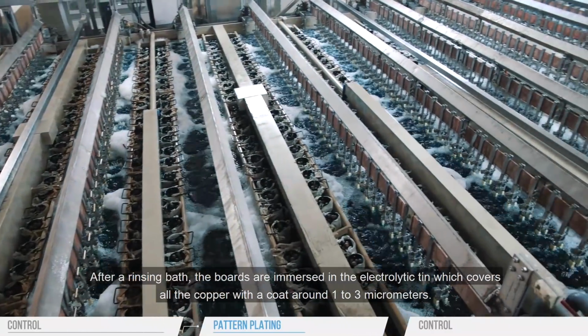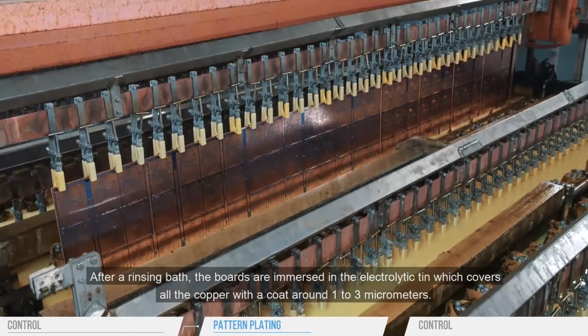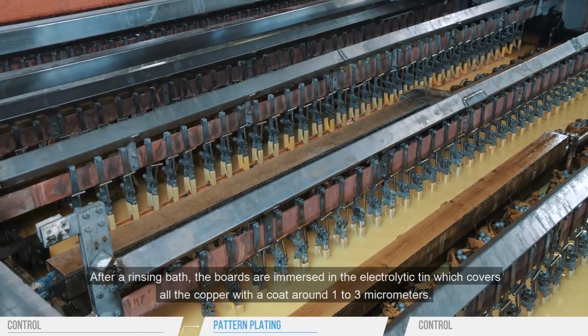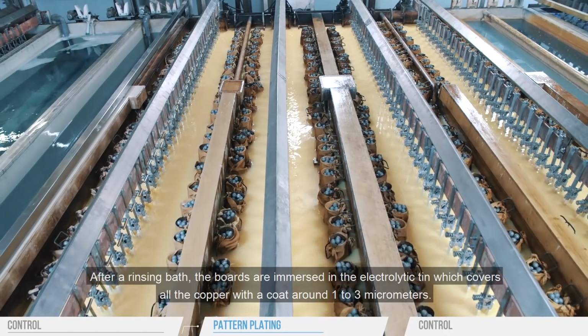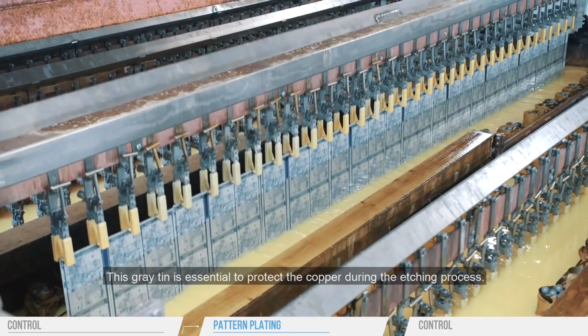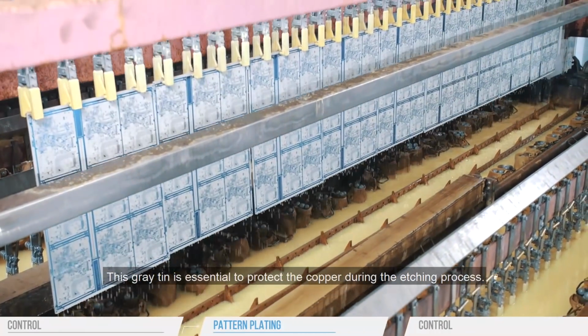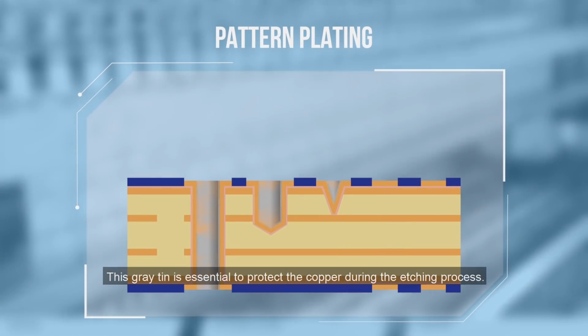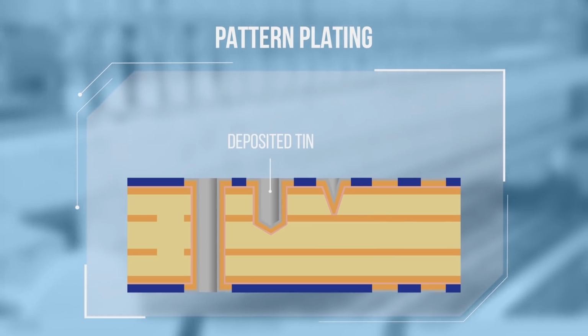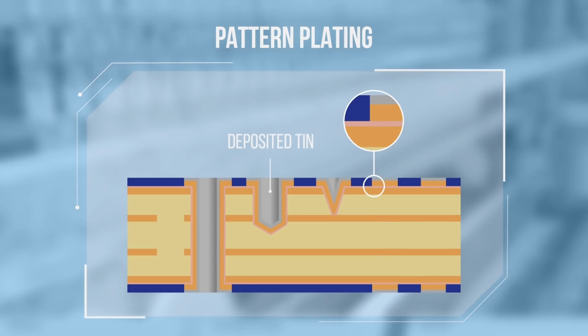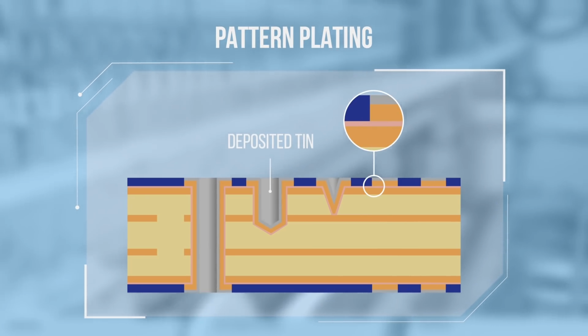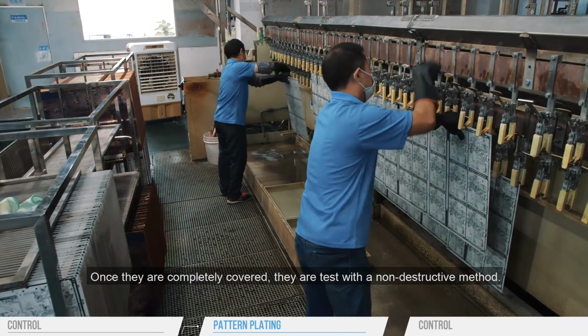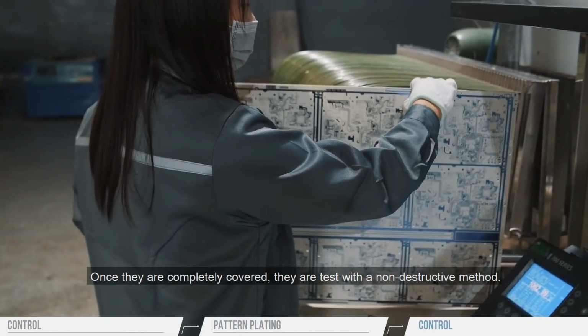After a rinsing bath, the boards are immersed in the electrolytic tin, which covers all the copper with a coat around 1 to 3 micrometers. This gray tin is essential to protect the copper during the etching process. Once they are completely covered, they are tested with a non-destructive method.